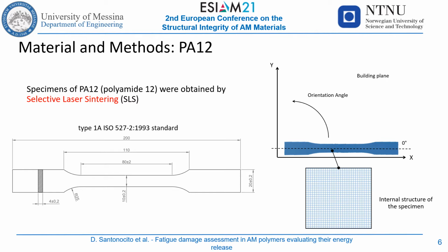The specimens were produced according to the geometry prescribed by the ISO standard, with a nominal cross-section of 10 by 4 mm, adopting the EOS commercial powder PA 2200. The specimen's building orientation angle was 0 degrees with respect to the X machine direction, allowing a volume internal grid-like structure due to the orthogonal laser beam trajectories.